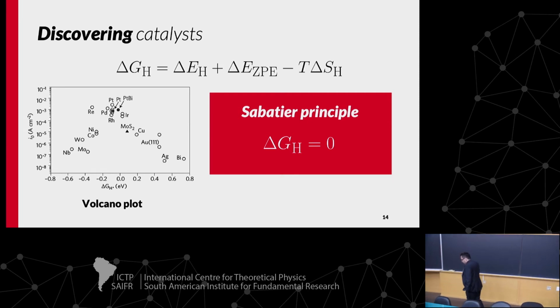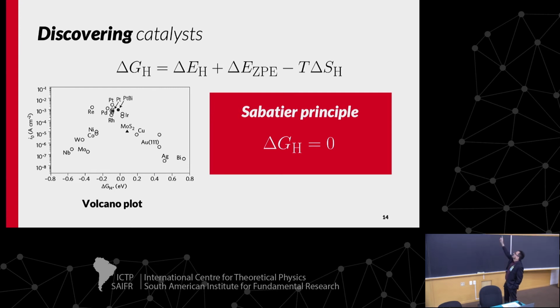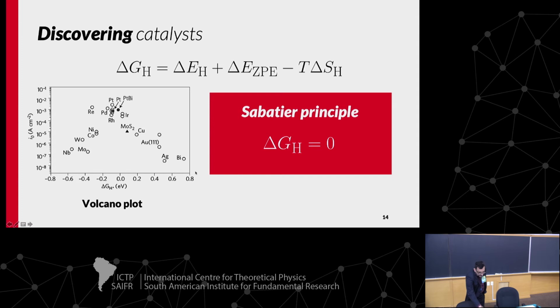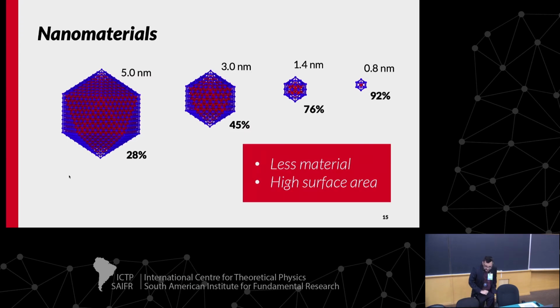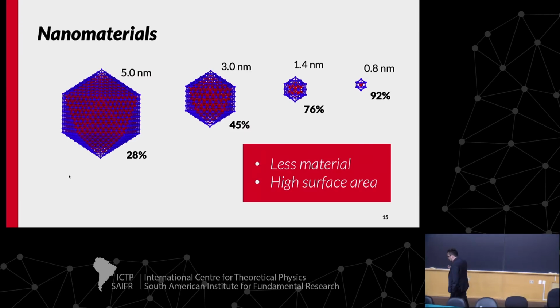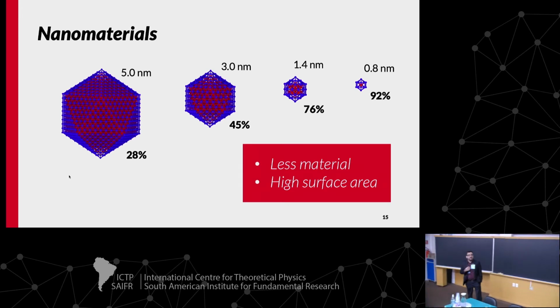When you calculate this, there is a principle called the Sabatier principle. It says that the catalysis for hydrogen evolution reactions is optimized when delta G is very close to 0. Here, on the x axis we have delta G calculated from ab initio calculations, and the y axis is experimental data.